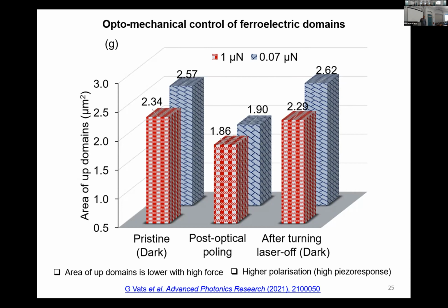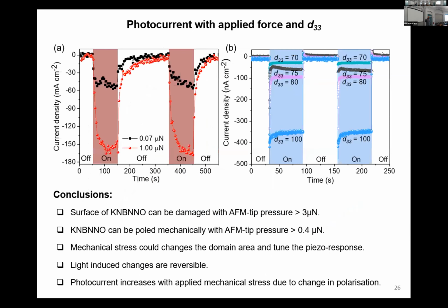I haven't shown here, but actually the PFM amplitude changed here again, and we got higher polarization, high piezo response, and as a result, we should expect a higher d33. Therefore, there should be a high photocurrent, and that's what I got in the next measurement. So you see, with different loads, the photocurrent was different, and if we compare with this previous data, where I was using different d33 to get different values of photocurrent, this is quite comparable. Here we are not compromising the contact area, basically the electrode and ferroelectric contact area.